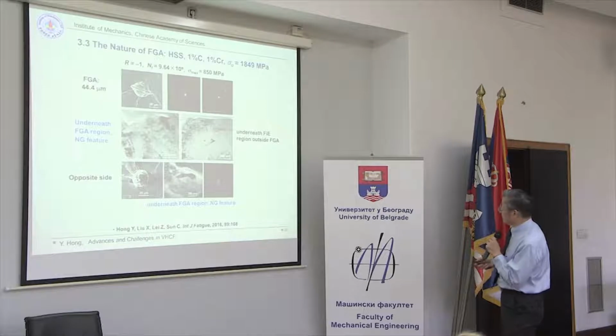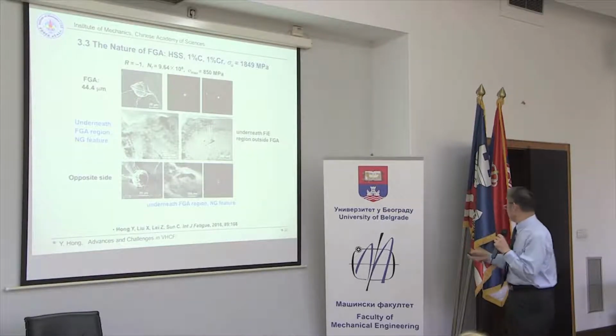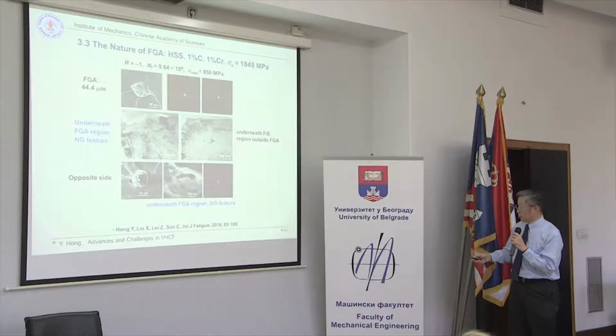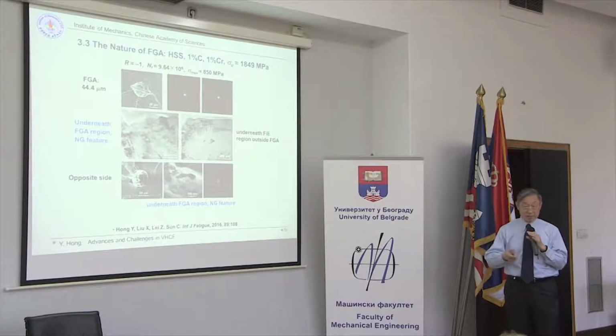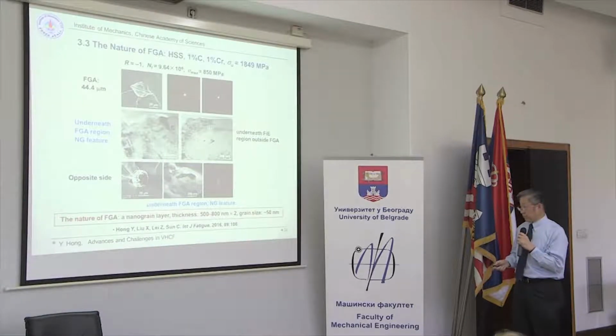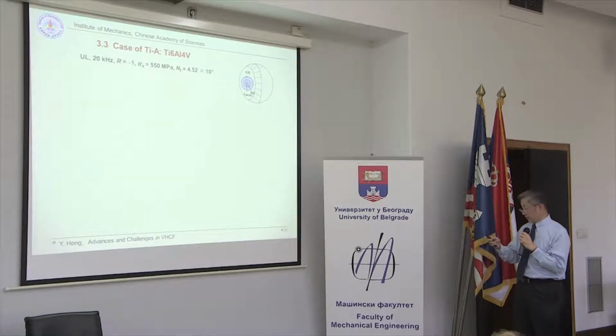It's not very clear, but we can see it's a continuous diffraction at the initiation region for both surfaces. But away from the initiation region, or just after or beyond this region, is a single grain diffraction. So we said the nature of FGA of this initiation region is a nanograin layer. The thickness for high strength steel is several hundred nanometers on both surfaces, and the average size is about 50 nanometers.